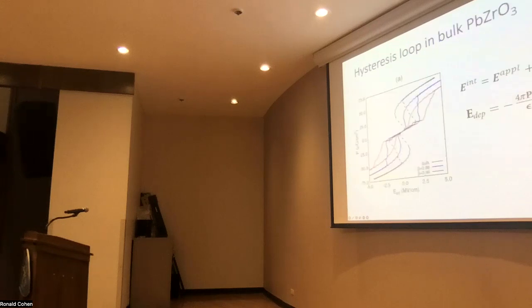We tried all that, and the result was very boring because every time in lead zirconate we will see loops like that. By the way, this is effective Hamiltonian finite temperature simulations. So every time we will get the response like that, which is red, which doesn't have any negative slopes. And then we recall that what happens in ferroelectrics, it's oftentimes the role of depolarizing field that brings us into that negative response region. So we decided to just bring in the depolarizing field in this case and see what's going to happen.